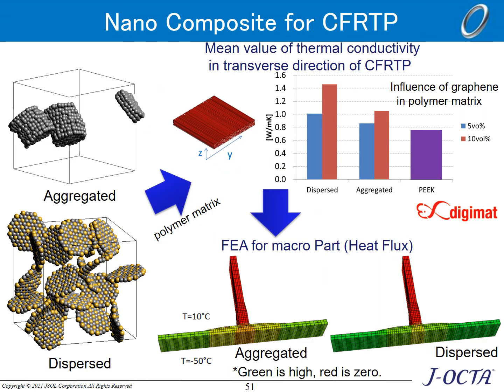Here are the results of the calculations. The figure on the left shows the dispersion structure of the graphene sheet in PEEK resin, calculated using DPD. The upper image shows a normal graphene sheet and the lower one is modified with oxygen. The yellow particles represent the oxygen. The introduction of oxygen causes the graphene sheet to disperse.